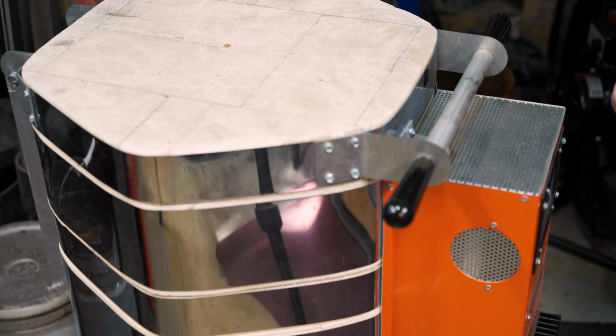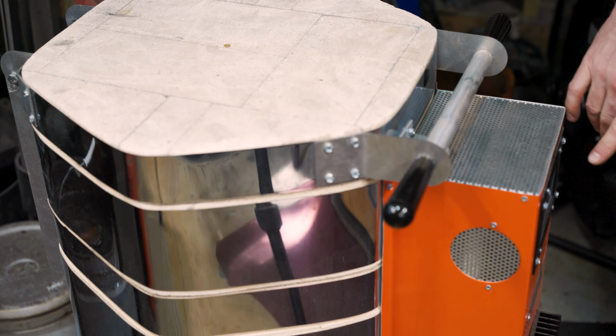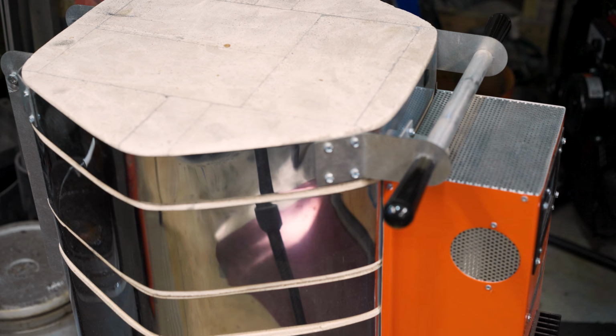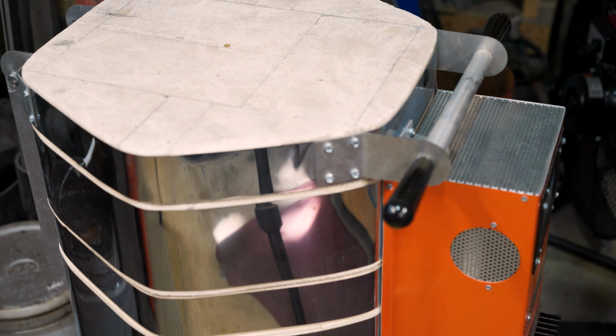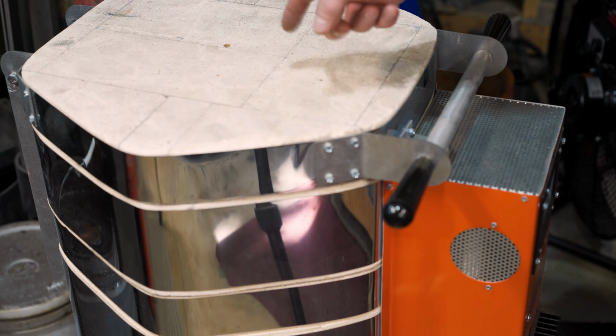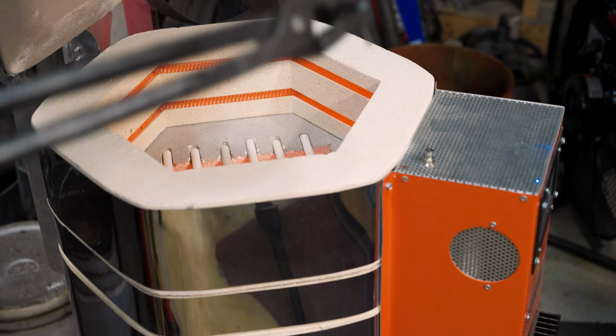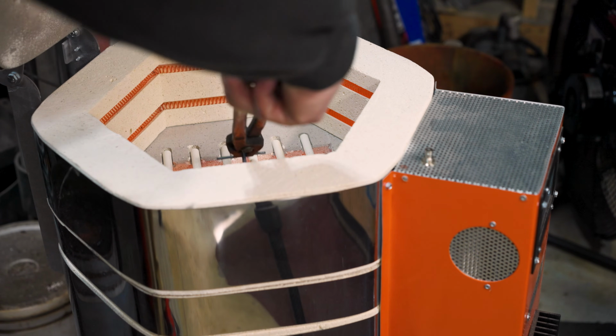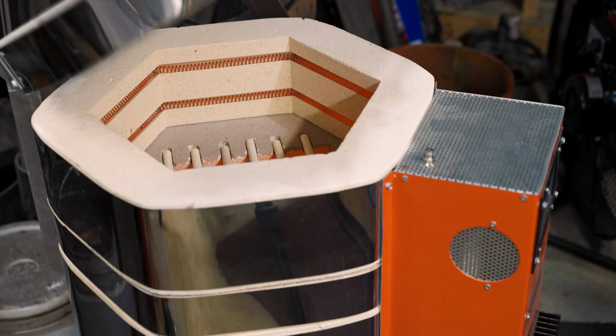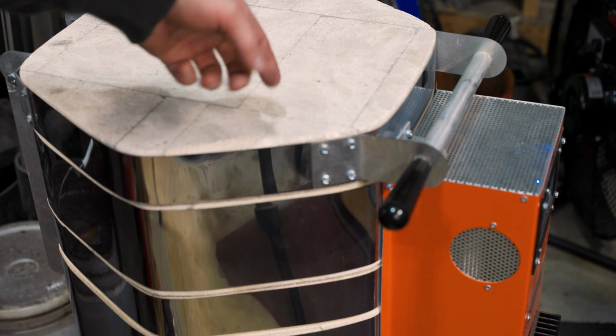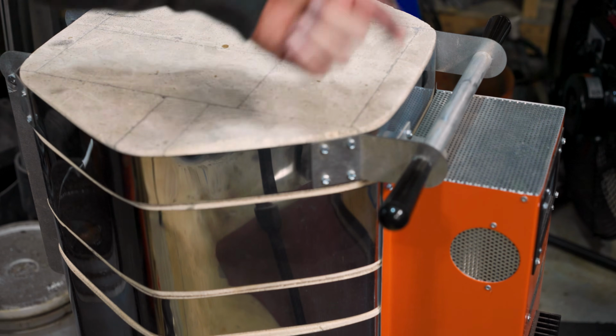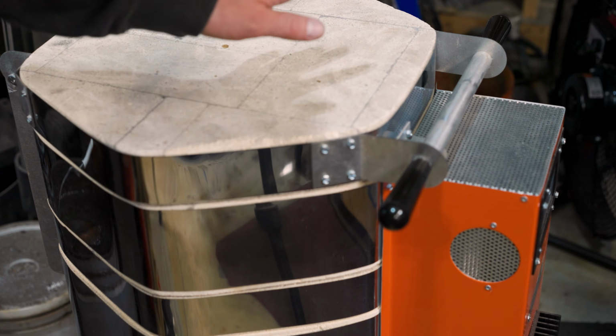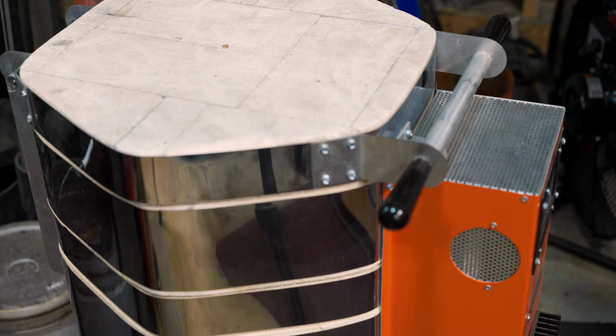And the kiln's at a little over 1300 degrees right now. So it's a good time to pull the knife back over and throw it in the kiln. And we've cooled the black, so pop that in there. Let it heat to 1500, and then we'll pull it out again, put it on the cooling rack until it's black, and heat this to 1350.